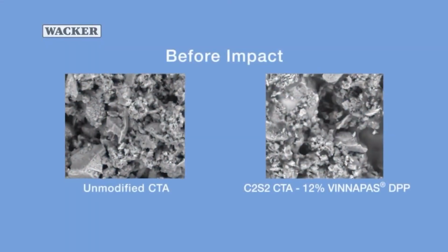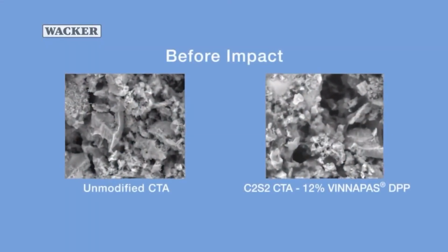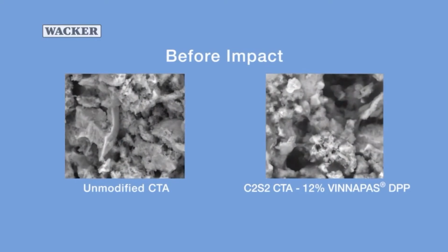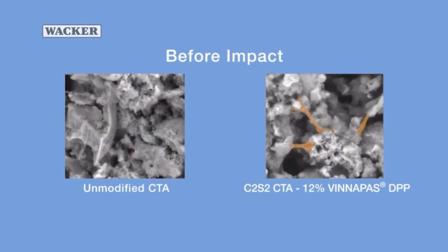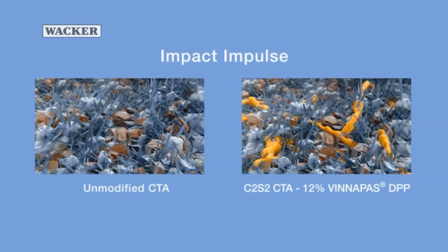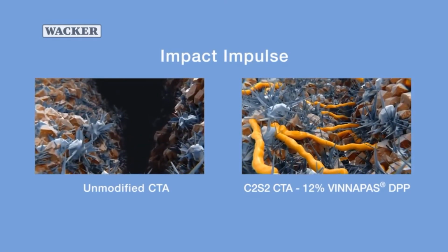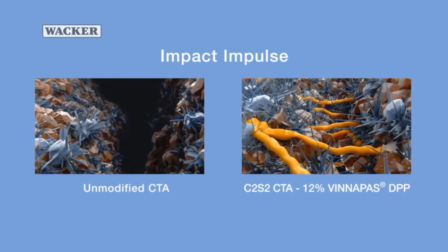Here you see the difference between the unmodified sample on the left and the specimen containing 12% VINNAPAS dispersible polymer powder, both prior to impact. This animation shows how each adhesive absorbs the force of the impact impulse. In the polymer-modified sample, the polymer bridges hold the adhesive together. Microscope images show that this is indeed what happens.